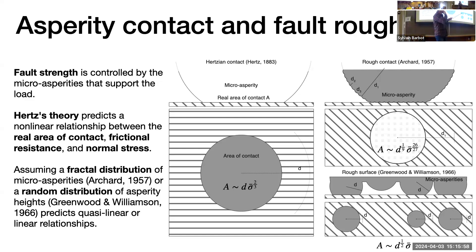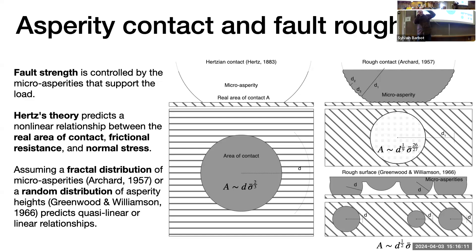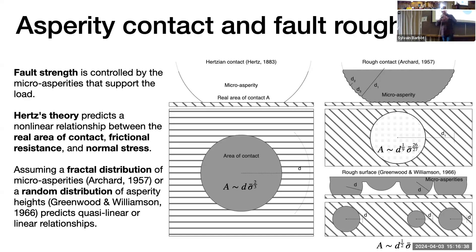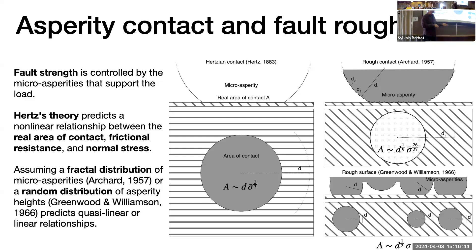The effective area of contact now scales almost linearly with normal stress — exponent 26/27. You can also randomize fault surfaces: along a long surface there are many micro-asperities, but with an overall long-wavelength topography, so they start to come into contact from different heights. When you randomize the starting heights of micro-asperities with the same radius, the average area of contact is exactly linear with normal stress — which is what Leonardo da Vinci and Amontons said.